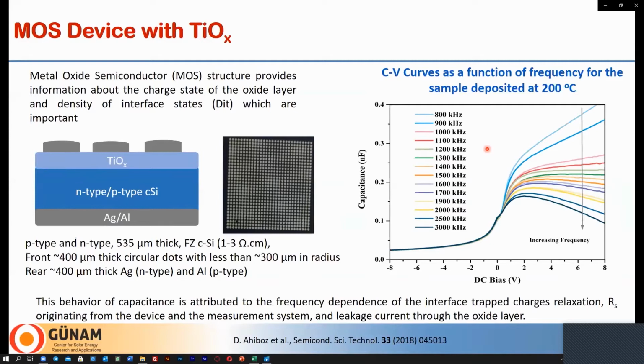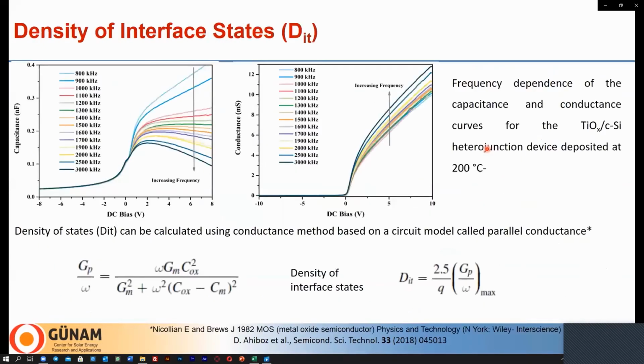So it's not very easy to model CV data, but we tried to understand and extract some information from them. Both CV and conductance results are shown here as a function of frequency, and from this data you can extract the density of states, which is an important parameter in solar cell applications. This can be calculated using the so-called conductance method, which is based on a circuit model called parallel conductance.